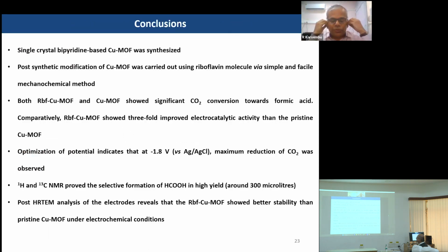We have shown that compared to the pristine MOF, the riboflavin modified MOF can act as a better catalyst for the reduction of carbon dioxide to formic acid. We prepared and modified the MOF under very mild conditions, analyzed and quantified the product, and found the Faraday efficiency of the catalyst to be good.